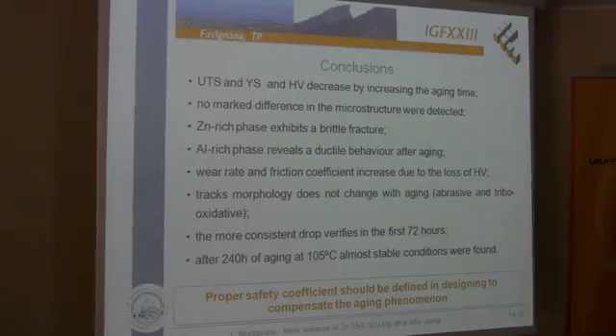The wear behavior is worsened by the aging, as the friction coefficient and the wear rate increase. And this behavior is probably related to the decrease of the mechanical properties, as the morphology of the wear track doesn't change with increasing aging time.